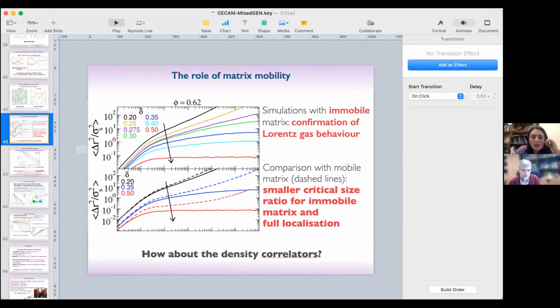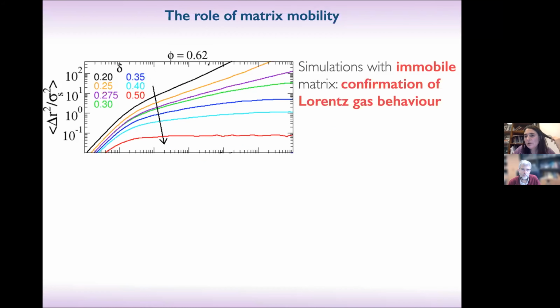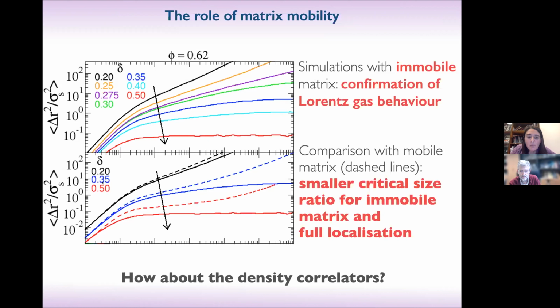So if I show this one, you see that we were at 0.62 packing fraction of the large. So you would expect that they are really frozen. But nonetheless, the small particles, even if they are still just 50%, can still diffuse a little bit. I'm not saying that they reach a diffusing behavior at long times, but still you don't find the caging. But this is an effect of three dimensions, because in three dimensions, even if you make a random close packing of the big spheres, you still have big holes. And that's what the small spheres exploit. But if you are in two dimensions, probably this mechanism is strongly suppressed. That's a very good suggestion, and I invite the next generations to study the two-dimensional model of this.